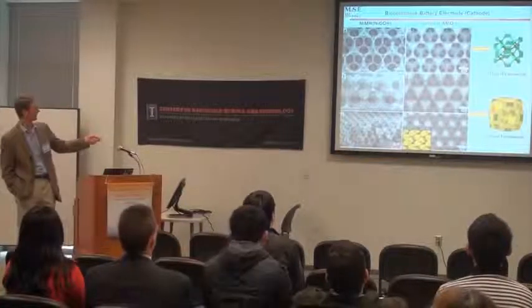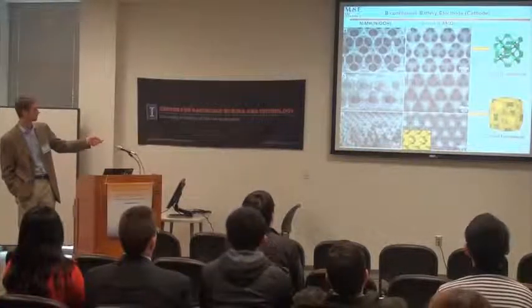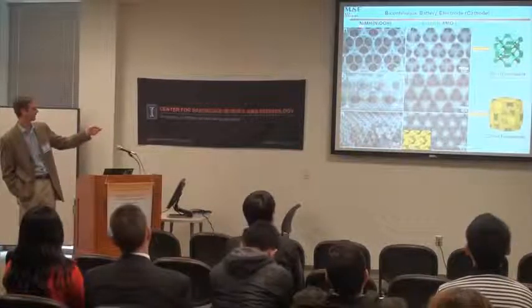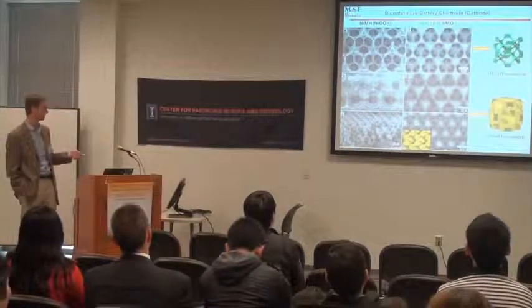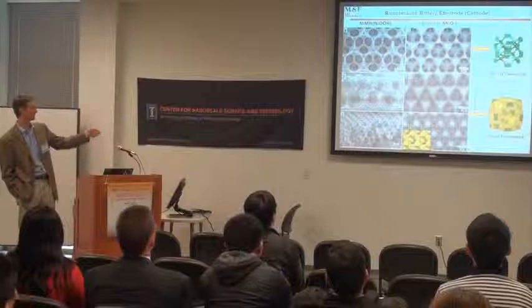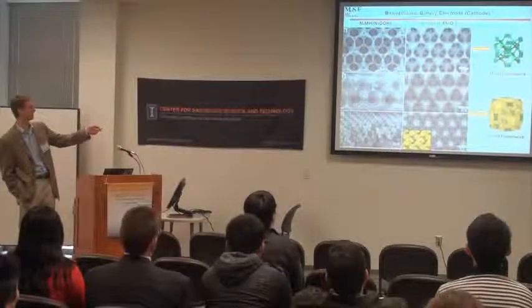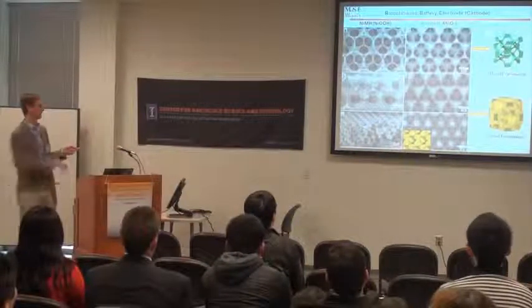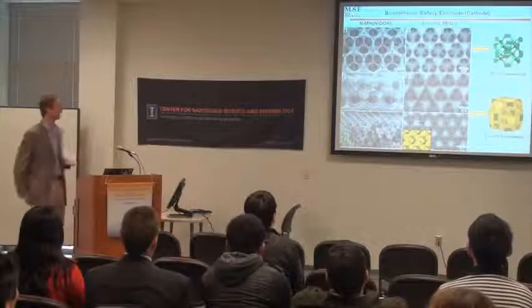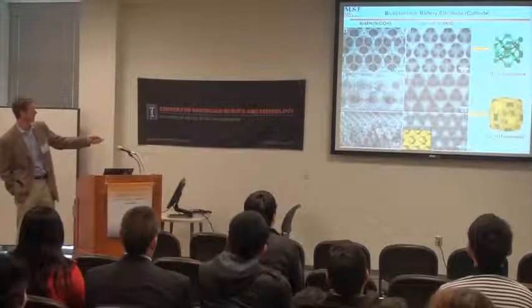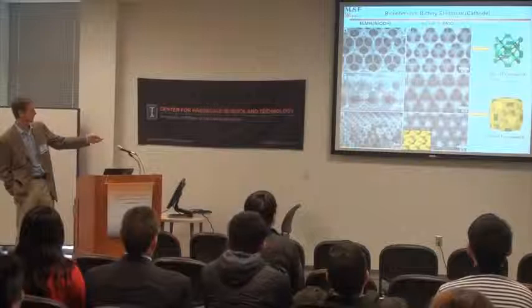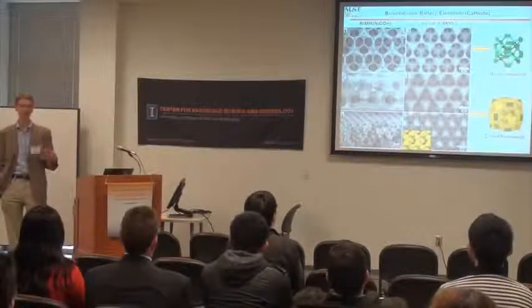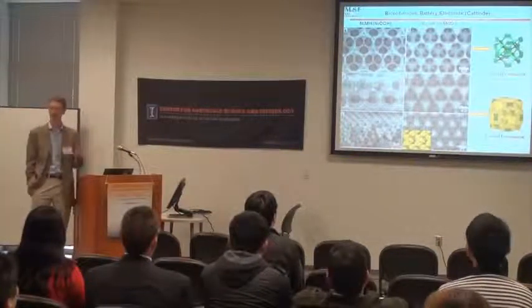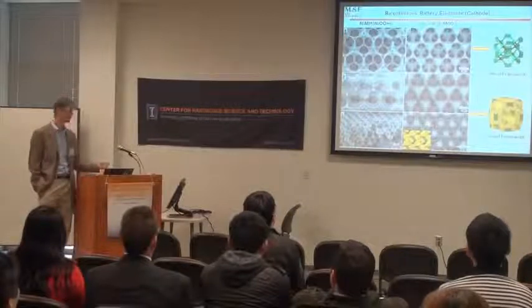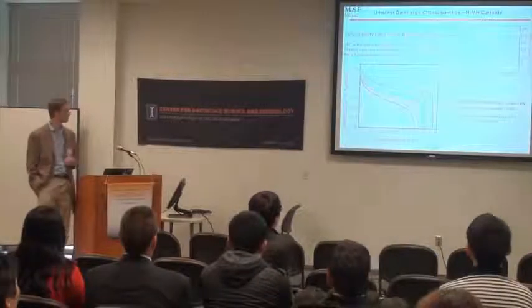In the battery design, now this is the active material. These are just SEM micrographs, and we made both nickel metal hydride and lithium ion systems. It's just a difference whether you're storing the energy in nickel oxyhydroxide or, in our case, lithiated manganese oxide. Again, you can see the coated framework, but this is the stuff that actually stores the energy. Everything else is just providing the electrical and the ion transport.